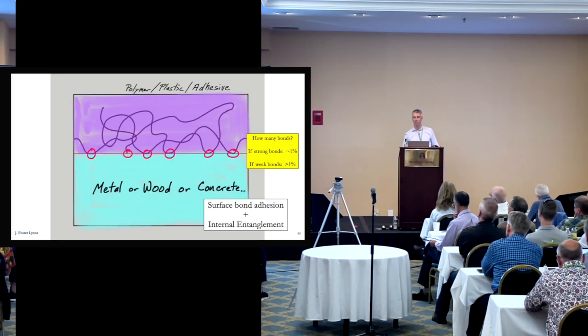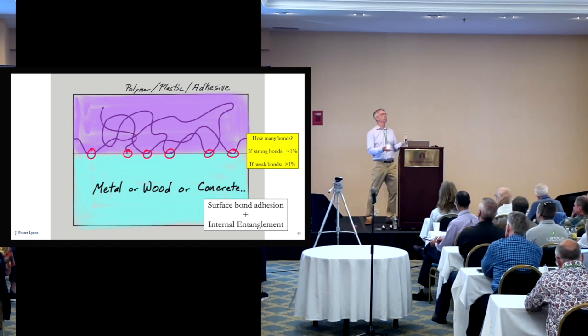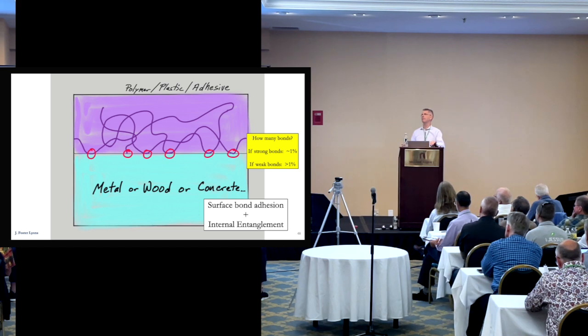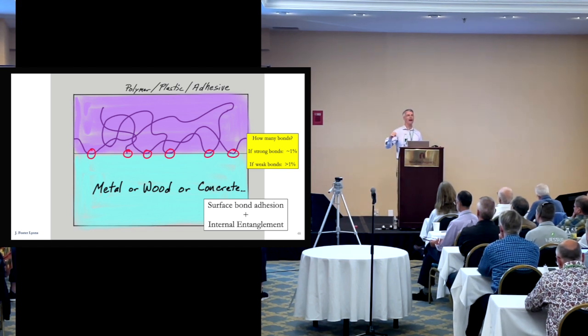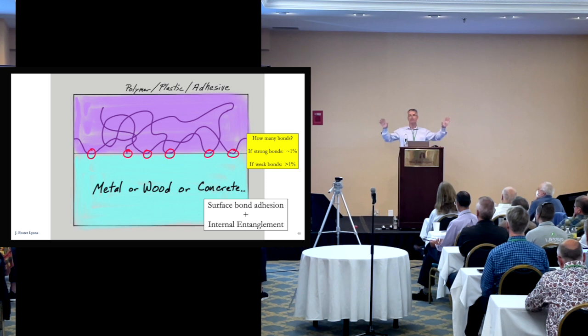So the question becomes, all right, how many of these surface energy bonds? And you're like, wouldn't more be better? And if we have more, why don't we make them super strong? Let's figure out the chemistry and make it really super strong. Turns out that's a mistake. You're better off having a lot of weak surface energy bonds than having high energy, hard to break surface energy bonds, like what we would call chemical bonds. If you have more than about 1% of strong bonds on this interface surface, your adhesion is poor. It's just not going to be practical. It turns out it's too stiff. You need weak bonds. So about 1% is what works best.